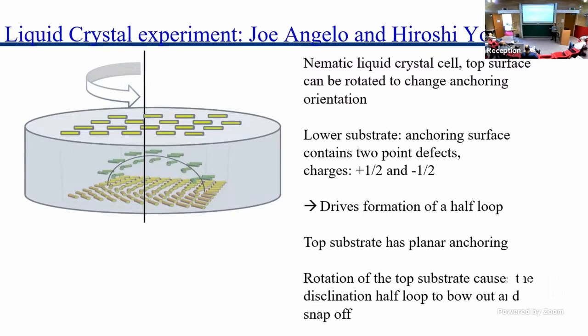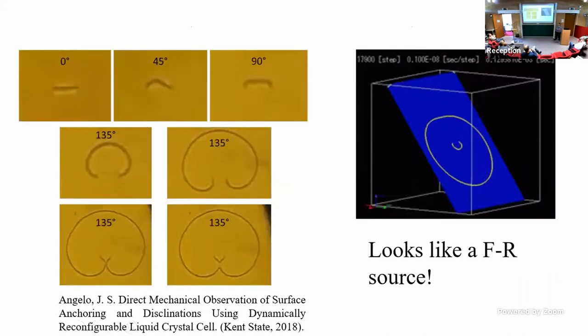Okay. And then they rotated the anchoring, or actually they rotated the bottom with respect to the top. The key issue is they twisted them. And what they saw was that the dislocation half loop dragged sideways. And they were doing this experiment to try to measure the line tension and other properties of the line defect. But then I saw the results in Joe's dissertation defense, and I saw these pictures and I said, that looks just like a Frank-Read source. And I said, Joe, you did an experiment where you demonstrated that a nematic liquid crystal can have a Frank-Read source. And his response was, what is a Frank-Read source? He'd never heard of it.